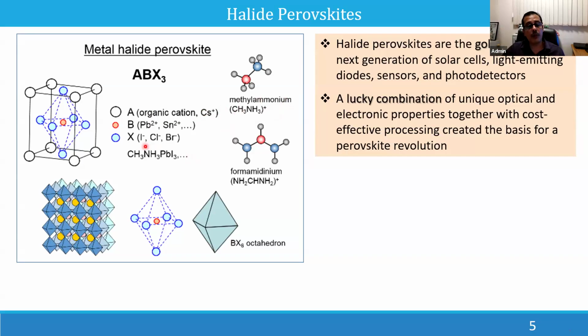One of the most popular hybrid perovskites is methyl ammonium lead iodide, which is giving something like 25-26% efficiency in solar cells. The structure is again the same as the ABX3 structure. Here the B cation occupies the middle of the octahedron, and the octahedron is formed by 6 halide anions. Several of these octahedra are joined together to form a three-dimensional structure, and the voids formed by this octahedral 3D structure are occupied by the A cation. So this A cation is either methyl ammonium or formamidinium, a small organic cation.